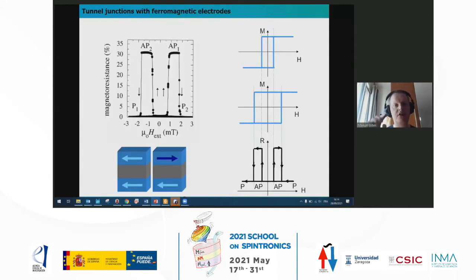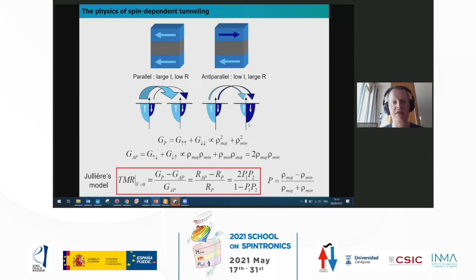So in magnetic tunnel junctions, this is a typical TMR measurement from back in the days, 1995, 1997. Cobalt, aluminum oxide, cobalt iron tunnel junction, where we had very square switching, and here about 30% of TMR. The TMR occurs basically because you have different resistance states when the magnetization of the two electrodes are antiparallel to each other, and this occurs in this small range of magnetic field.